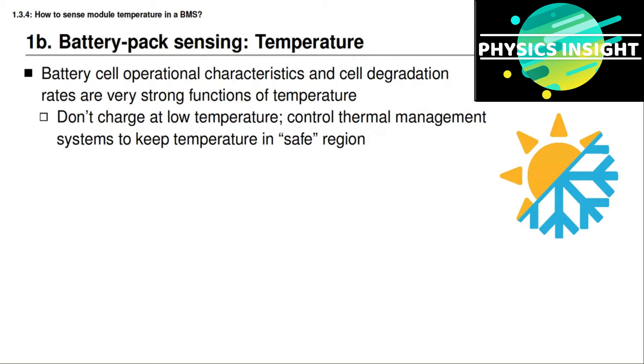You will learn more about this in the fourth course in this specialization when you learn about state of health estimation, but a phenomenon known as lithium plating can happen, which very quickly degrades the cell and can even result in a safety situation. So it's common not to charge lithium ion battery cells when the temperature is colder than about zero degrees Celsius.